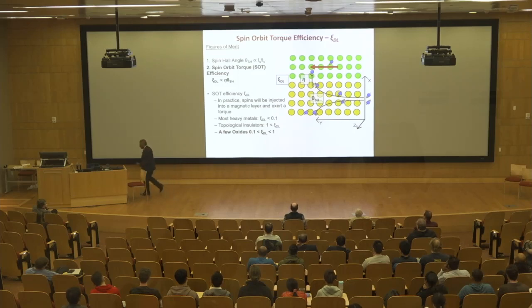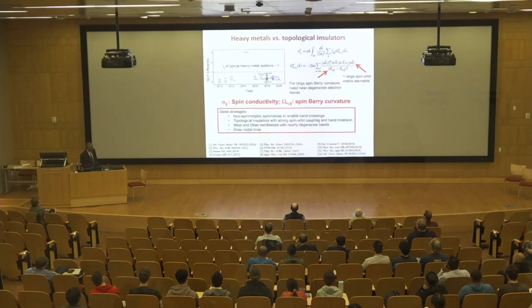So if you look at materials, people typically have used materials which have large spin-orbit coupling. And so if you look at this chart, it looks very complicated. It is very complicated. But you look at the spin-orbit torque efficiency, there's very few materials which have above 1. Platinum, for example, is 0.1.